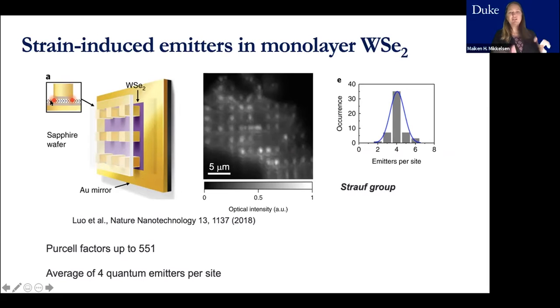On average, you can see the four corners of the cube are inducing about 4 emitters per site. And in this case, they observed Purcell factors up to 550, but they're not quite at the single emitter level, typically with 4 emitters per site. But I think it's a very exciting way that you can deterministically embed single emitters.